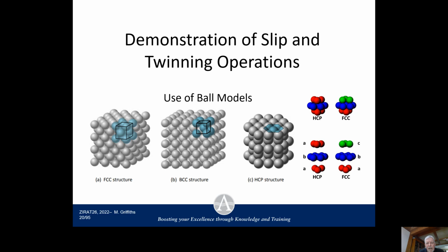If you put the atoms at certain positions, it's hexagonal, and at the alternate position, it would be face-centered cubic. So if we have ABC stacking, it's face-centered cubic. If we have ABA stacking, it's hexagonal. You may ask, why are you talking about hexagonal still? Well, my point is, you will see, because this relates to epsilon martensite formation,